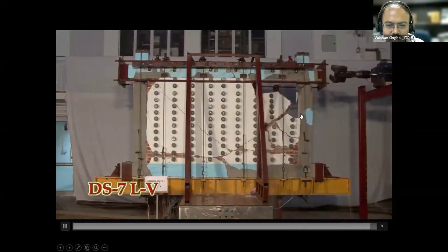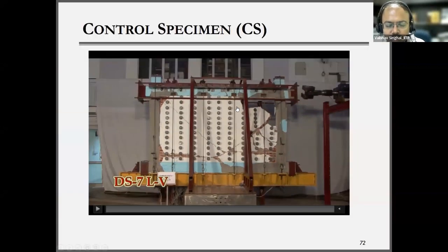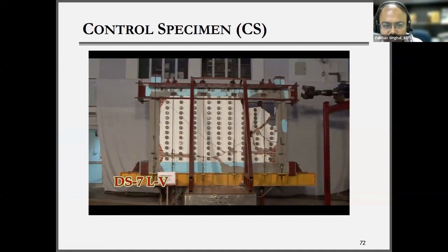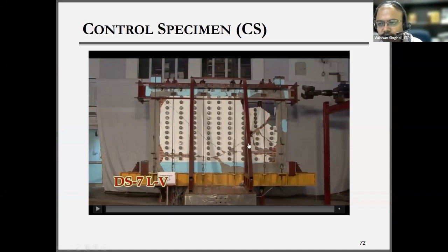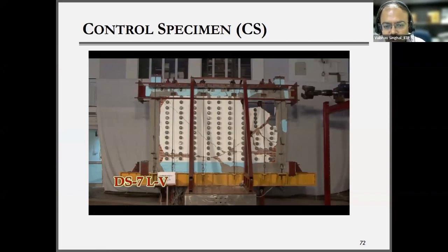In the next cycle, you will see the wall has almost been dismantled, or it has been coming outward. Because of some restraint from the out-of-plane support, the complete failure we have not seen, but the wall was almost on the verge of a complete out-of-plane collapse. So this is the response of a control specimen.